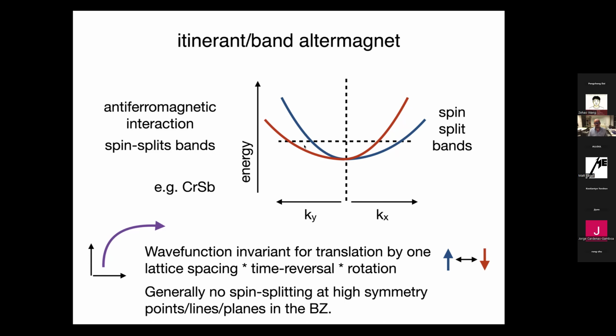So there is a splitting of the bands, except at high symmetry points. For instance, look at the center here, which could be the gamma point at k equals 0. At k equals 0, of course, rotation leaves the momentum invariant. So a rotation does nothing to the wave function, and therefore, in an altermagnet, also at gamma, the bands have to be degenerate. So there's, in general, no spin splitting at high symmetry points or high symmetry lines or high symmetry planes in the Brillouin zone, because these higher symmetries can protect the spin degeneracy.